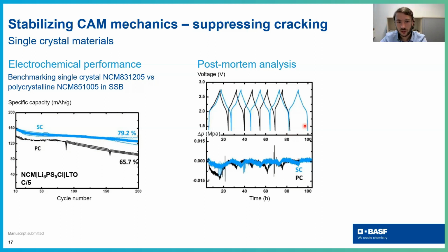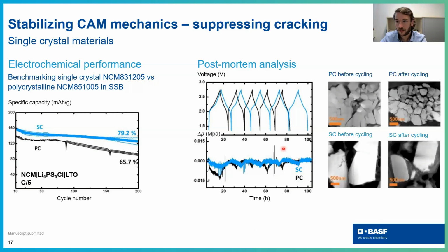And now if you monitor again the pressure of your solid-state battery, surprisingly, we see that the cell with the single crystal material, the blue line here, has less pressure changes during the charge and discharge, although you have actually higher capacities. And also the profile looks kind of more symmetric. And finally, if you open these cycled cells and look into the morphology, then you see that the polycrystalline material really cracks a lot after the cycling, and the single crystal material remains much more intact.